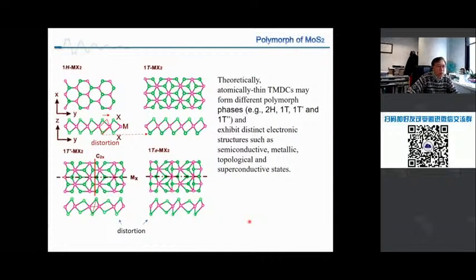I mentioned this 1T or 1T prime, which is a distorted phase. If we look at the cross-section views, you see the typical features as I marked here. The so-called 1T phase is simply a shift to the right side of the top layer, and you form this regular distorted structure. Or you make further distortion like this, a partially distorted structure, or further distortion, and you get a 1T prime or 1TD. Those materials show superconductivity, metallic properties, and topological phases because of the band structure, very recently.